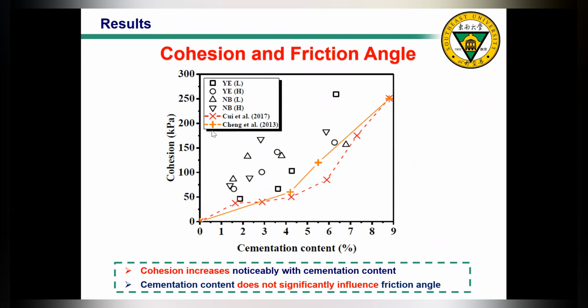Then, based on the direct shear test, we also obtain the cohesion and friction angle based on the Mohr-Coulomb theory. This graph shows the cohesion versus cementation content. Obviously, with the increase in cementation content, cohesion increases due to the formed interparticle bonding, so the improvement in cohesion is quite obvious. Compared with previous studies, at the same cementation content, the cohesion measured in our study is higher than in two previously reported studies, meaning that potentially this biostimulation method is more effective, because these two previous studies were all about bioaugmentation, not biostimulation.